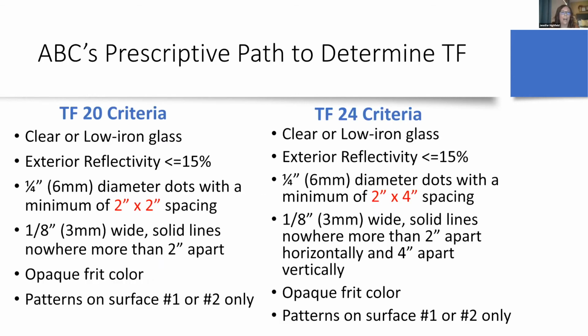And because it's not possible to test all screen patterns and color combinations, ABC has developed a guide to selecting a template called the prescriptive path to determining threat factor. If this criterion is followed, a bird is more likely to see the pattern and adjust its flight path away from the glass. The main difference between these two prescriptive paths is the 2x2 spacing versus the 2x4 spacing. Both of these options will comply with the local law 15. However, the closer 2x2 spacing will achieve a lower threat factor than the slightly larger spacing of 2x4.